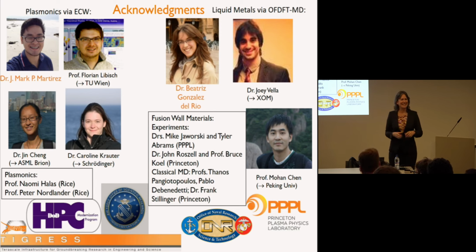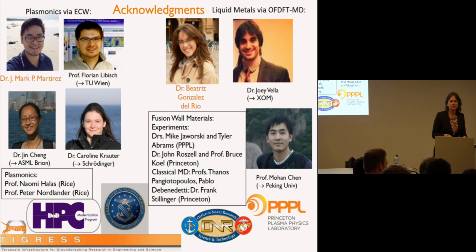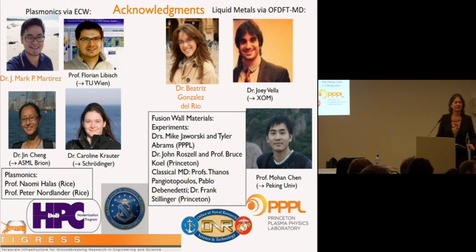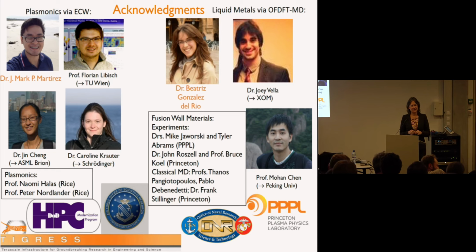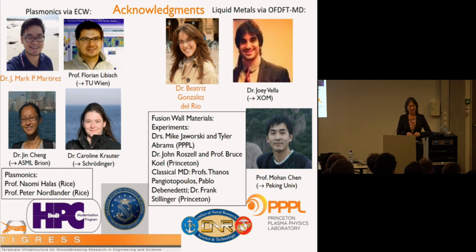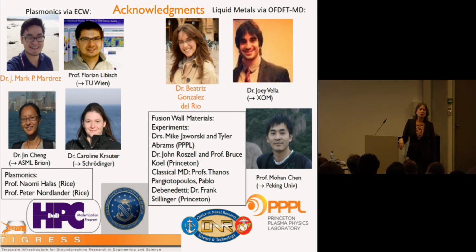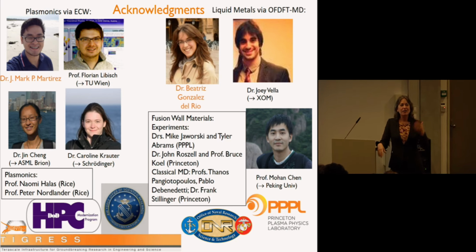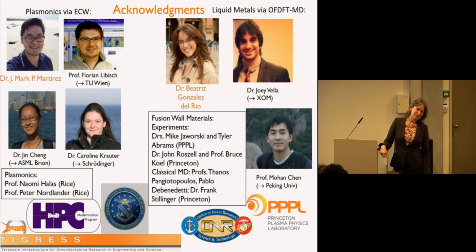Other questions? Yes. Maybe one question on the N2 dissociation. In the first step, the way you selected molybdenum embedded in gold as being good was based on this correlation between the dissociation energy and the barrier, right? It was one of the ways. But do you really need this constraint, knowing that you're going to use plasmonic states anyway? Well, I can tell you, we have another paper, which I didn't talk about, on iron doped into gold, and the barrier is higher there. So it works, but it's higher.